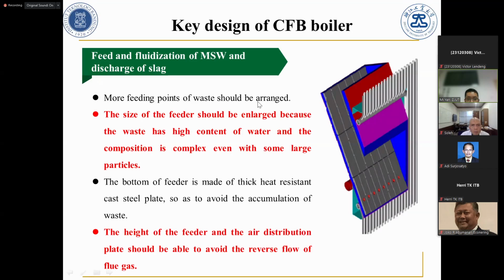More feeding points of waste should be arranged, so the mixture will be homogeneous, and the size of the feed inlet should be enlarged because the waste has high moisture content and the size is sometimes big, or the composition is complex, even with some large particles. So here it should be larger, and the height of the feeder and the air distribution plate should avoid backflow of the flue gas, because we have to avoid the flue gas going out through the feeder, right? So usually the feeder output is under the dense level, which means the waste is directly mixed with the sand in the bed, not over the fire.